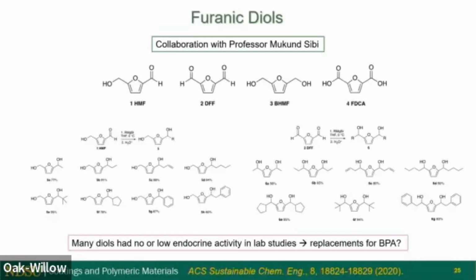And one of the things that Akzo helped us with was actually doing the endocrine studies to compare the endocrine activity with bisphenol A. So of course, bisphenol A has endocrine activity, and so there's a concern with bisphenol A in humans. And so we want to see, do these have any improved toxicology? And most of those diols either had almost no activity or very, very low activity compared to bisphenol A. So they could potentially be safer replacements for bisphenol A.